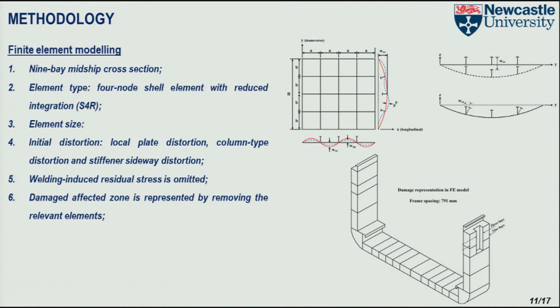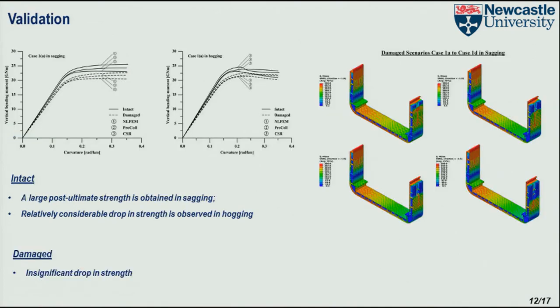You may find some uncertainty in the ultimate strength prediction. It is inevitable because there are uncertainties from the way we derive the load shortening curve and the way we calculate the overall hull girder response. But if you look at this table and these two figures, we can see that there's a reasonably close agreement in terms of the strength reduction between different methodologies. So that may give us some confidence to use the simplified calculation for predicting the residual ultimate strength.